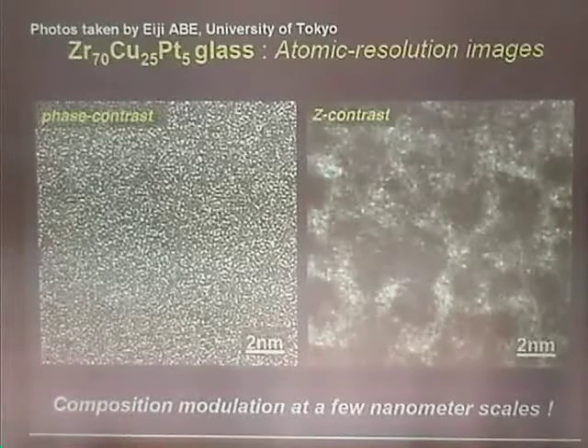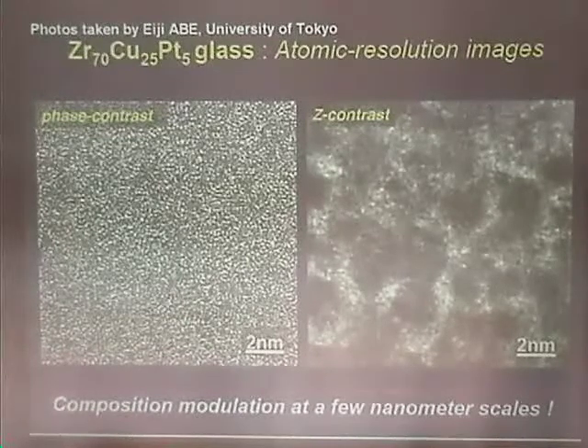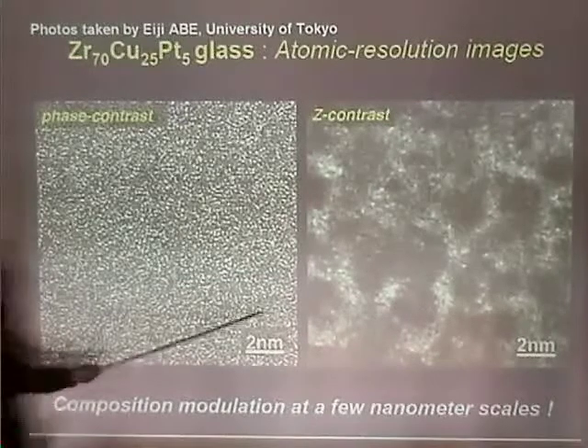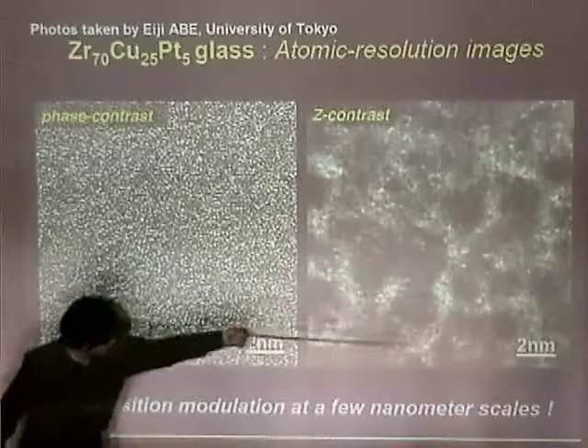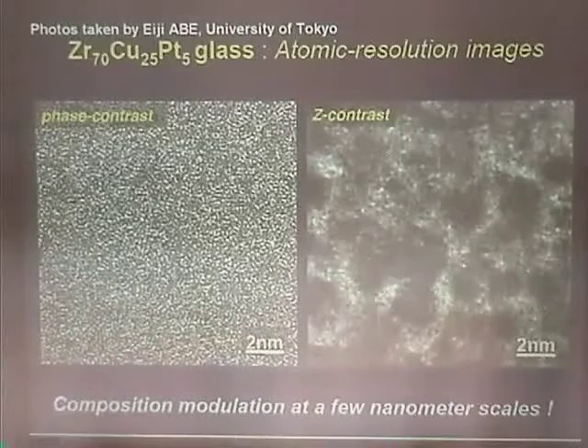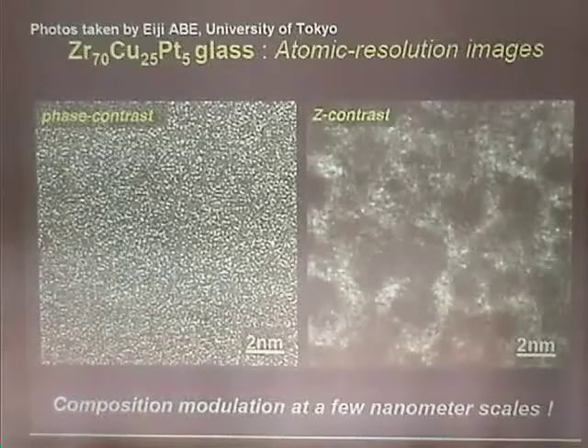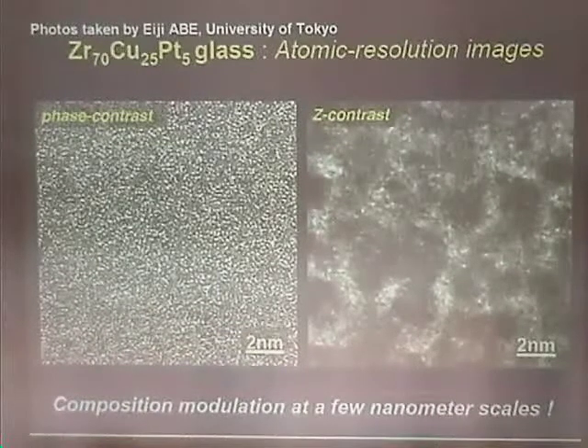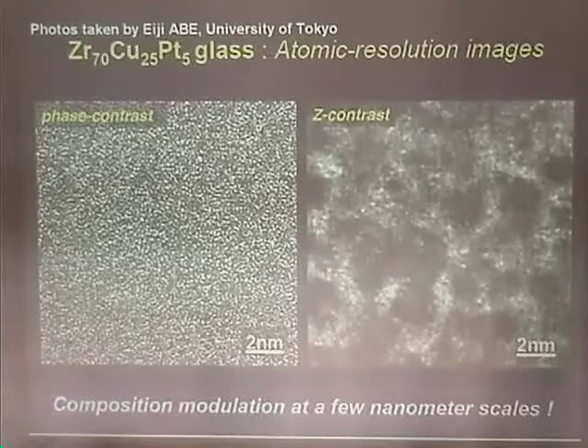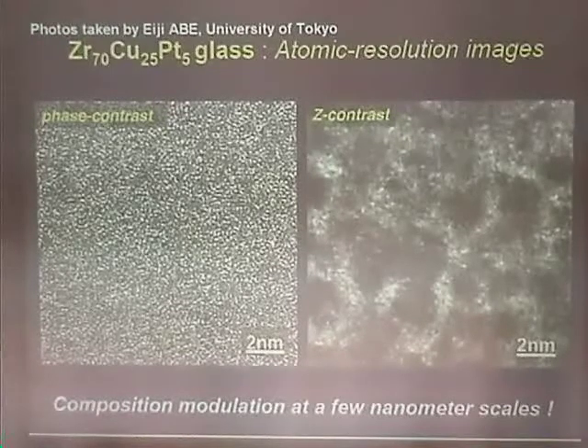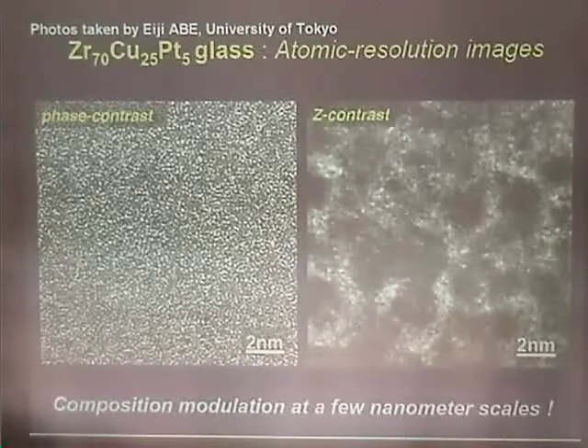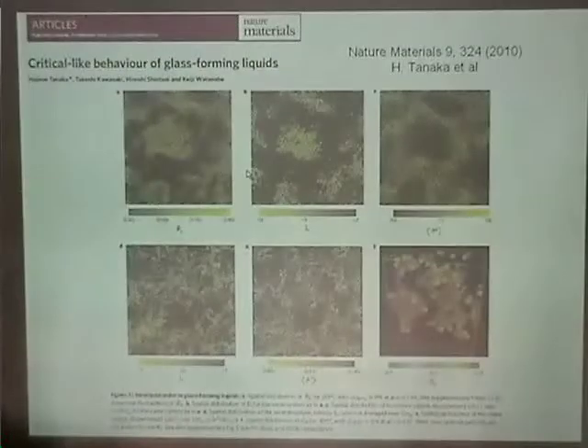Shorter wavelengths. So correlation length. I thought the zirconium ones didn't have this inhomogeneity that you were talking about before. I'd like to say that zirconium is farther down, more homogeneous. For the zirconium, the velocities didn't even go above ultrasound, so it was hard to extract the length scale. So if it happened, it happened.